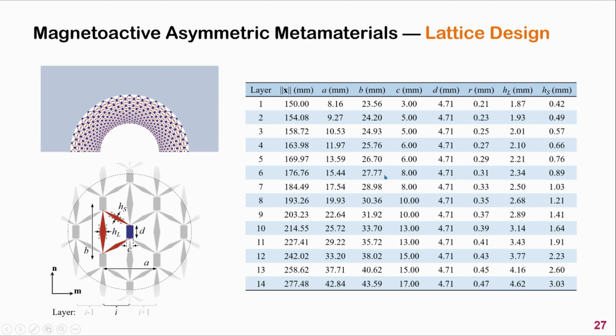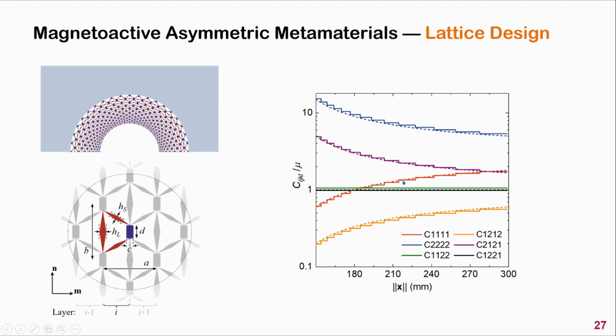Okay, first of all, let's examine the effective elasticity tensor of the microstructure in each layer. The numerically homogenized effective parameters are shown by the solid stepped lines, which agree very well with the analytical solution shown by the dashed lines that are given by the transformation method.